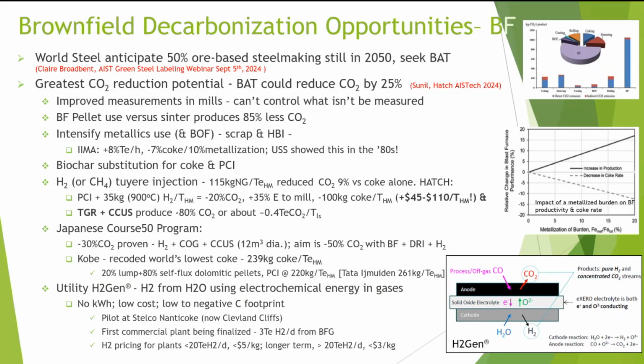Japanese Course 50 program, of course, has shown 30% reduction already, and they're aiming for 50%, moving from hydrogen, coke oven gas, and CCUS on a 12 cubic meter diameter furnace, a small one, to blast furnace plus DRI plus hydrogen. Kobe, we've already talked about their low coke rate, and they achieved that with 20% lump, 80% self-fluxing dolomitic pellets, and PCI at 220 kilograms a ton.